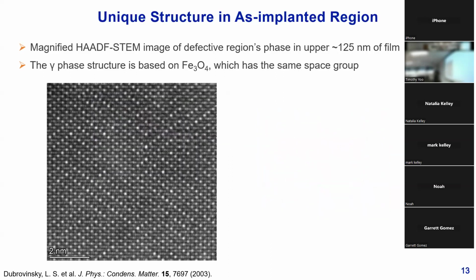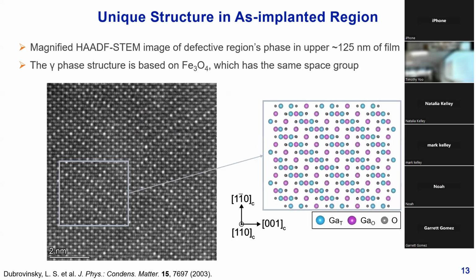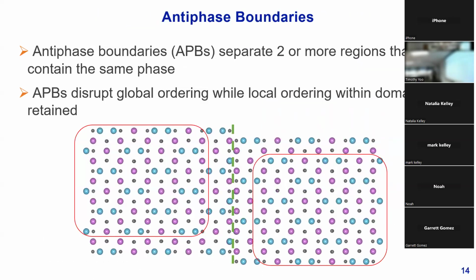And interestingly, throughout the entire defect film, we can see that most of the structure is characterized by this unique defect arrangement with these streaking features. And we can see here that by building a model structure that's actually an overlap of two gamma sheets on top of one another, we can get pretty good agreement with the experimental results, namely with these streaking bright individual atomic columns and in those triplets. And so what we see here is that upon further analysis, this is actually due to anti-phase boundaries.